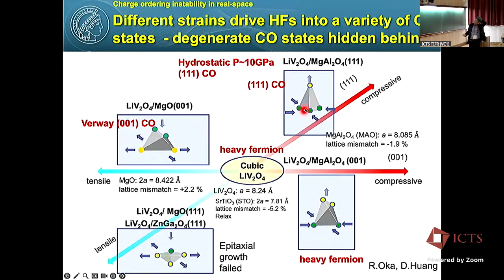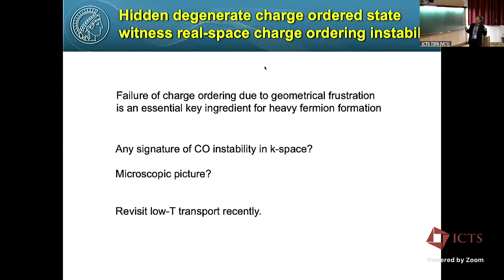Now we prepared a different kind of substrate and tried to see what's happening. For example, instead of 001 magnesium oxide, we put on a 111 substrate, magnesium aluminate, and then we saw a different kind of charge order, 111 charge order. We applied hydrostatic pressure, and we found another type of 111 charge order structure. So at least we found three different charge order structures. So I cannot claim macroscopic degeneracy, but at least we saw three. And we believe we found hidden degenerate charge ordered states. And of course, it witnesses a real space charge ordering instability. So it is a failed charge ordered insulator.